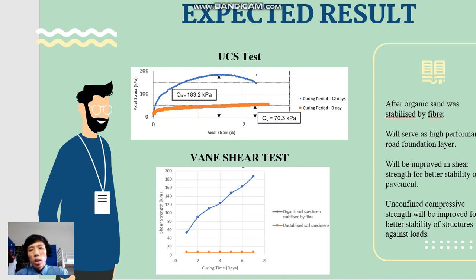From the UCS test, it can be clearly seen that the qu axial stress of the sand sample at curing period of 12 days is higher than at curing period of 0 day. The 2 samples are mixed with humic acid and also fiber. This shows that the strength will increase if the curing period is increasing. Next is the vane shear test. The organic soil specimen stabilized by fiber shows an increase in shear strength, while the unstabilized soil specimens remain constant along the 7 days of curing.